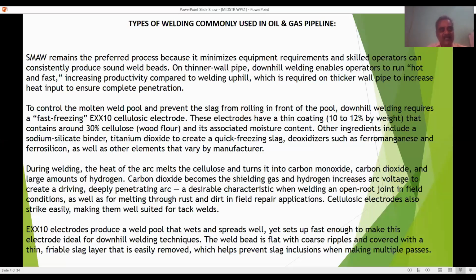During welding, the heat of the arc melts the cellulose and turns it into carbon monoxide, carbon dioxide, and large amounts of hydrogen. Carbon dioxide becomes the shielding gas and hydrogen increases arc voltage to create a driving, deeply penetrating arc. A desirable characteristic when welding an open root joint in field conditions, as well as for melting through rust and dirt in field repair applications.